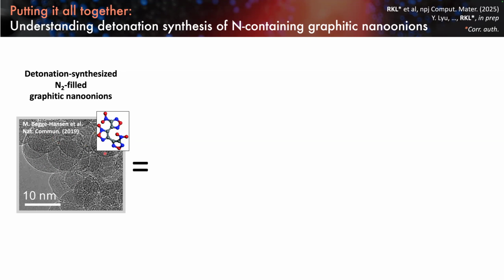When you detonate a material, it's very similar to what happens during a shock experiment. You're going to reach some sort of peak temperature and pressure - we call that the Chapman-Jouguet point. Once you hit that pressure, you're going to sit there for a while, and then everything is going to thermally and mechanically relax to ambient temperature and pressure.